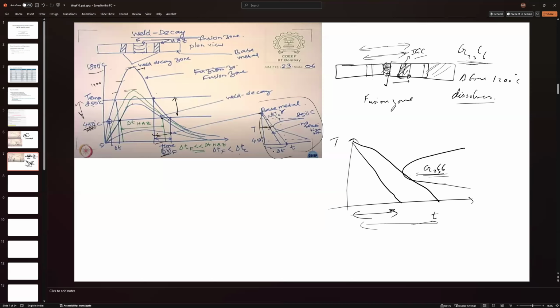Between those two times, delta T HAZ, you're getting precipitation of the chromium carbide, so you get a lot more time. So the cooling is a lot slower, and you're spending much more time in this zone where chromium carbide is precipitating out. So here your sample is getting more sensitized toward IGC.